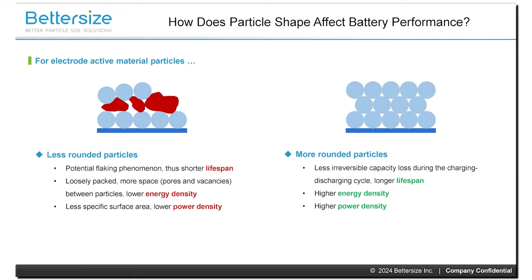And this improves the battery longevity and reliability. In terms of cycling stability and lifetime, particle shape impacts how effectively the electrode material accommodates volume changes during charge and discharge cycles. Shapes that minimize these stress concentrations and maintain structural integrity over multiple cycles can enhance the battery's cycling stability and extend its operational lifetime. So, careful consideration of a particle shape allows for the optimization of these factors to achieve batteries with improved energy density, power output, durability, and overall performance.